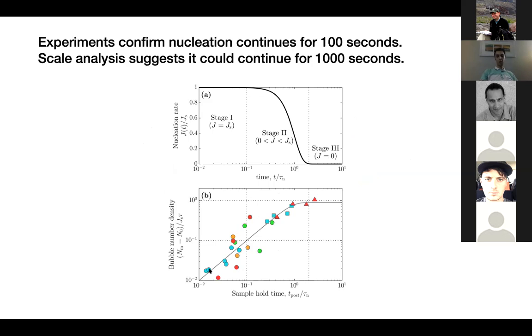When we plot observed bubble number densities, scaled non-dimensional, with samples' annealing time or hold time scaled by a nucleation time scale, we see bubble number density is proportional to samples' annealing time. This nucleation time scale is basically the time scale that determines how long it takes for diffusion to become effective and reduce saturation pressure.